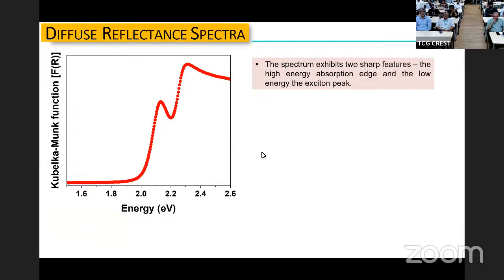The band gap. Let us talk about the band gap. This is the absorption curve, and I told you the absorption curve gives me an estimate of the band gap right in the beginning. You can see two peaks here. This is the exciton formation, and this is the free carrier generation absorption edge.